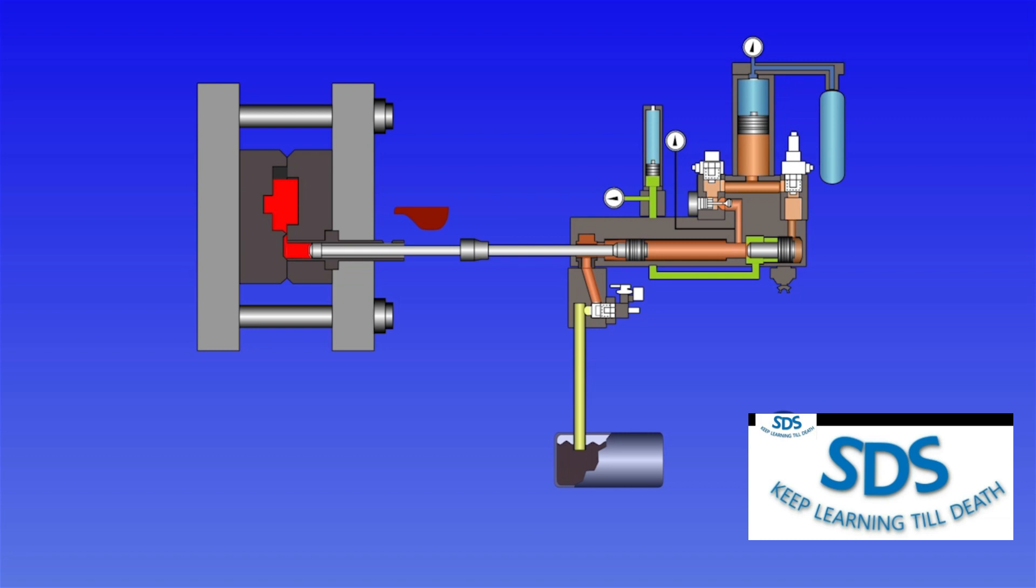Typically, this phase of the injection process requires 4.5 or 5 meters per second in order to fill the die before the metal starts to freeze inside the die, causing cold shuts or lamination.